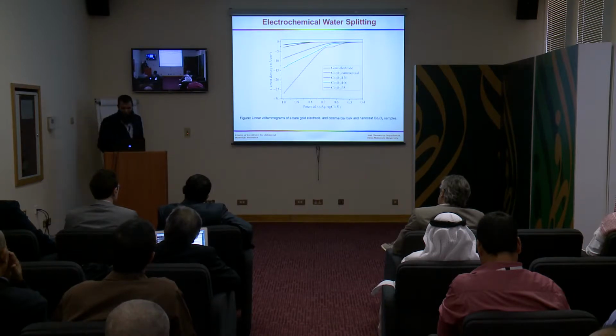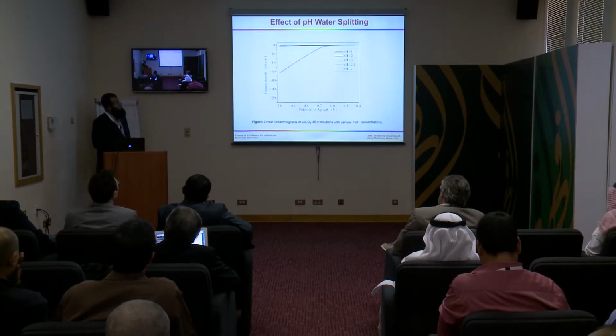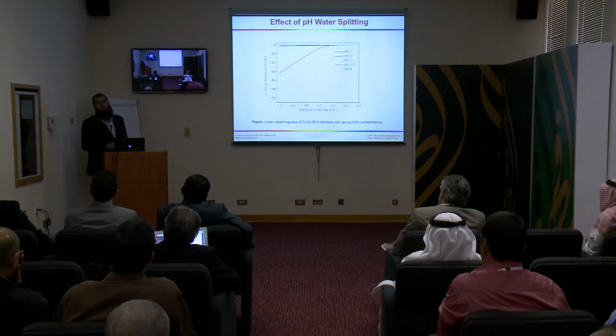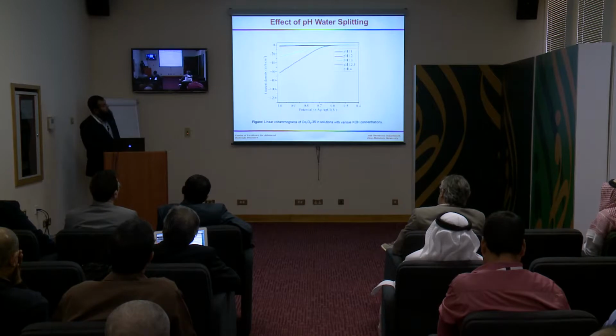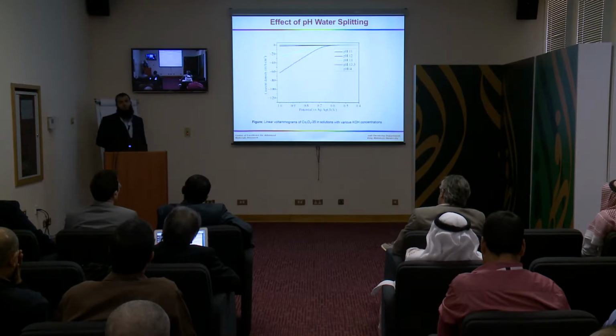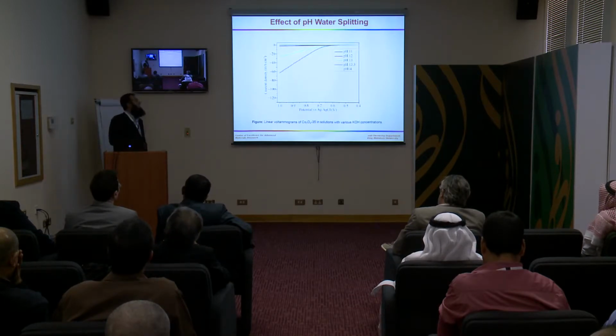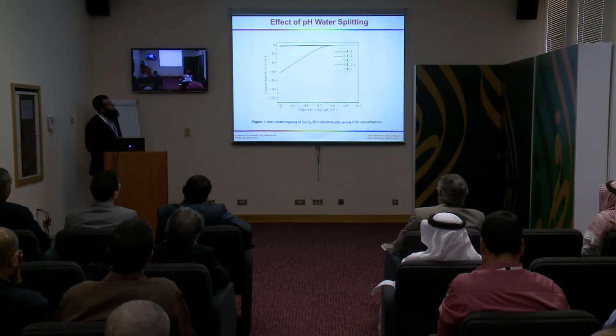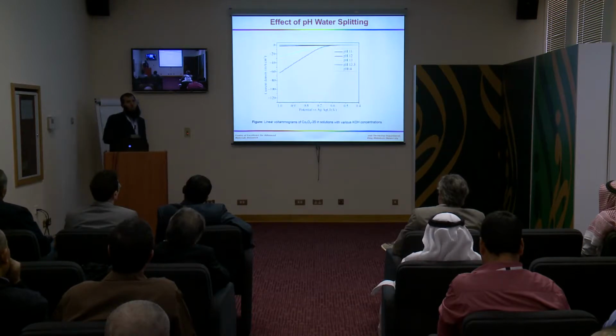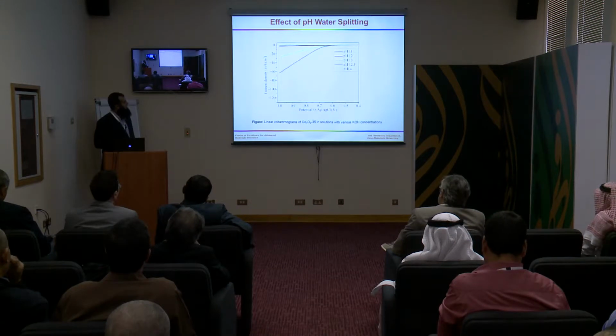Then we selected this material and tested it at different pH using different concentrations of OH electrolyte, and we found that when we increase the concentration of electrolyte, the current density increases and the overpotential is reduced, because the OH ion in the electrolyte may be interfering in this system. That's why it increases the current density.